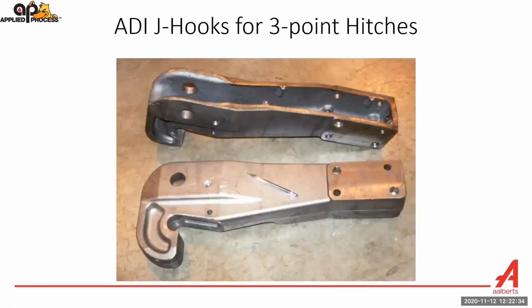On the back of tractors, the J hooks for 3-point hitches are oftentimes made out of Aust-tempered ductile iron. There were some very unique design considerations done here. Notice that the inside of the J hook is hollowed out. They put the material where it was needed. And also on the bottom of the J hook, it is scalloped out to reduce mass and section size as well. So this was lightweighted.